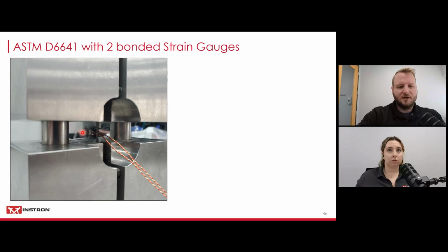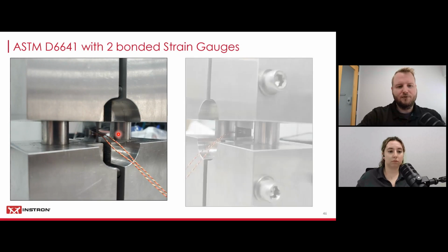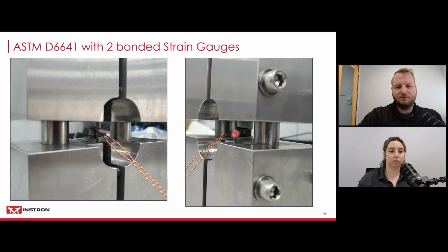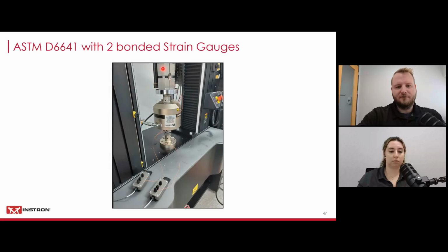And then this is a close-up on both sides of the specimen here with the strain gauges and the cables coming out. And then I place the fixture like that in between the platens, and then you've got the cables here leading into our conditioning electronics, as we've showed earlier in the presentation. So these need to match the strain gauges that you're using on your specimen. So these are also configured for a 350 ohm quarter bridge setup.